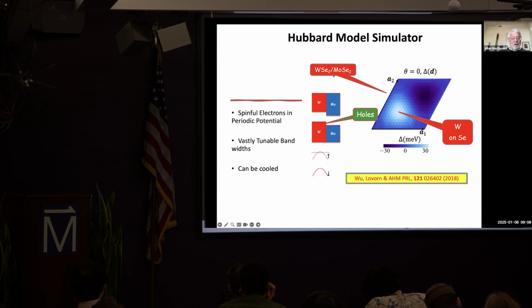So two different materials, so that the electrons or holes, the relevant states at the top of the valence band. In this sketch here, this is energy vertically and position horizontally, tungsten or molybdenum layer. And so the states are basically in the tungsten layer, but they see a weak potential due to the molybdenum layer. And if I look at the energy of the top of the valence band as a function of the stacking between the layers, that tells me that the energy here varies by something on the order of 100 meV, or let's say in this calculation, 60 meV.